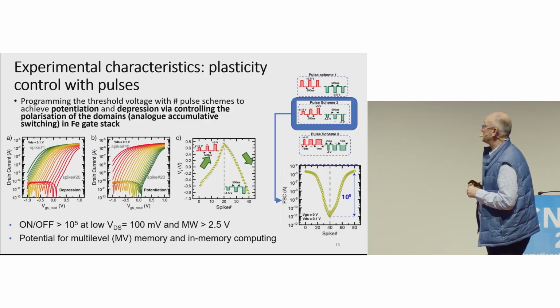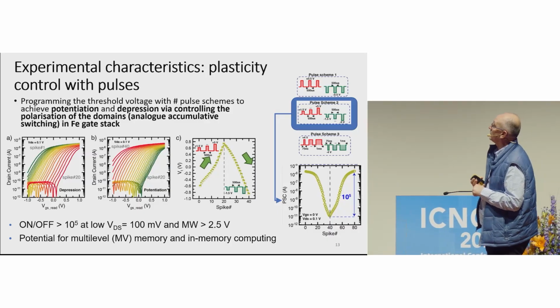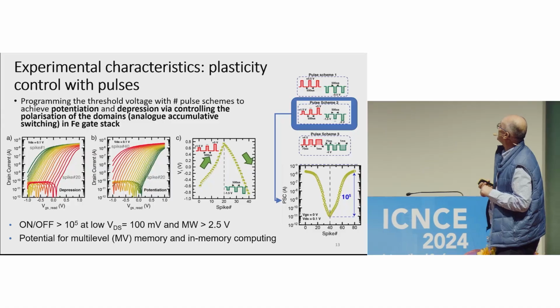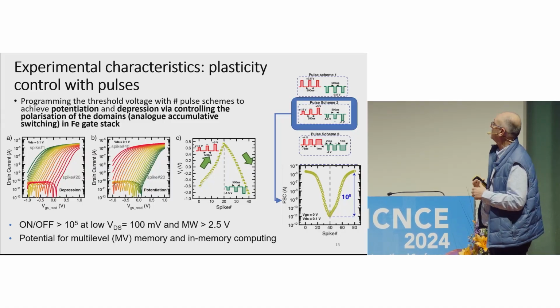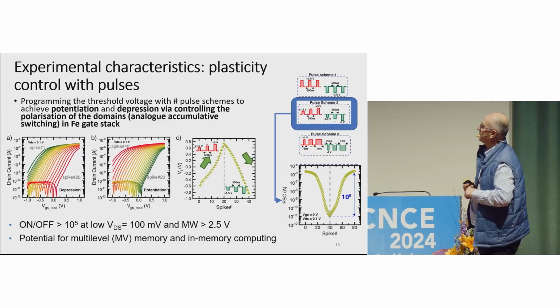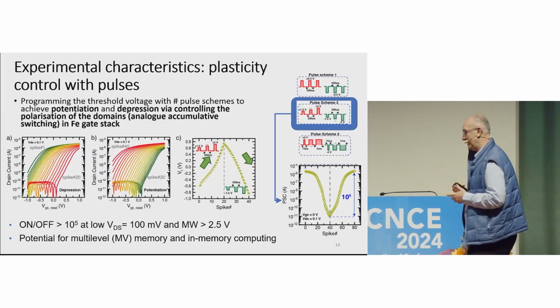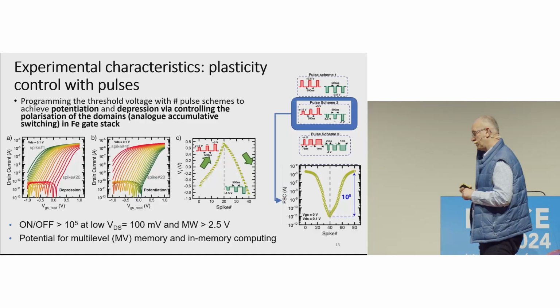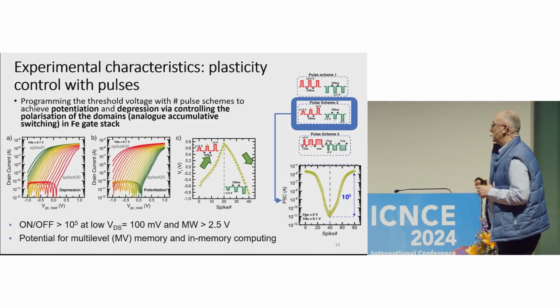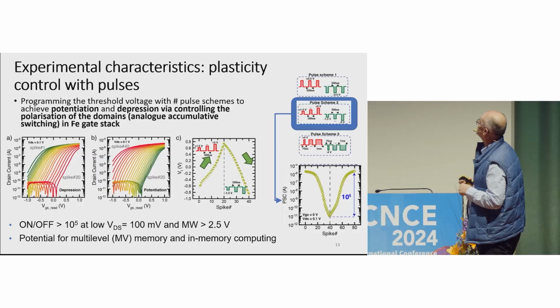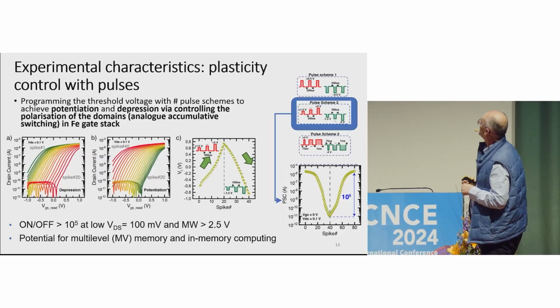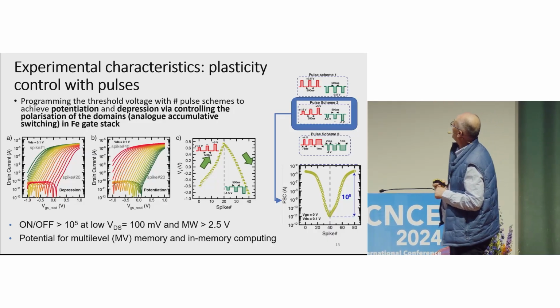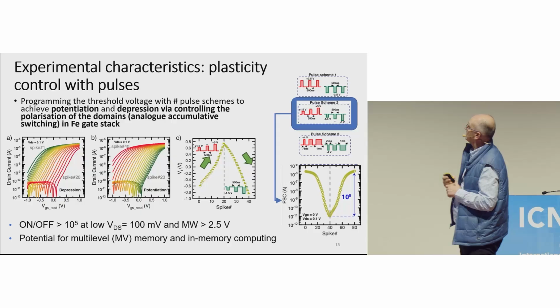And this is absolutely possible. It's amazingly nice and easy to achieve it. So you see here different pulse schemes that we have used in which you have to very carefully tune the parameters. It depends a lot on the characteristic of your ferroelectric, the dipole response, and the domain and the size of this domain. But here, as you see, with pulse schemes varying from 3 to 5 volt, and with pulses going from tens of nanoseconds to microseconds, we achieve with pulse scheme number 2 a full potentiation